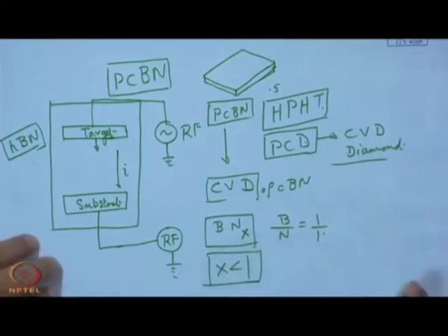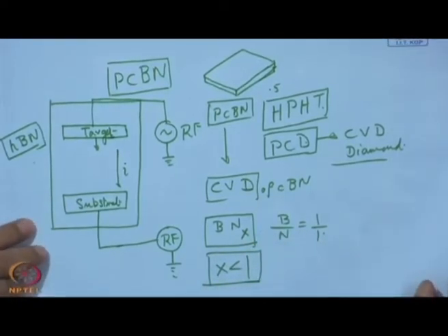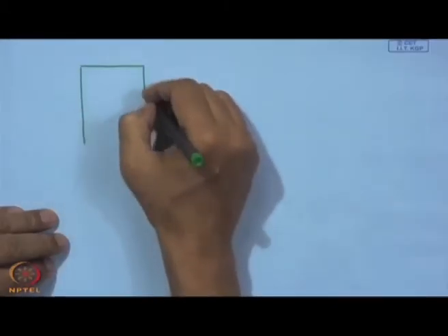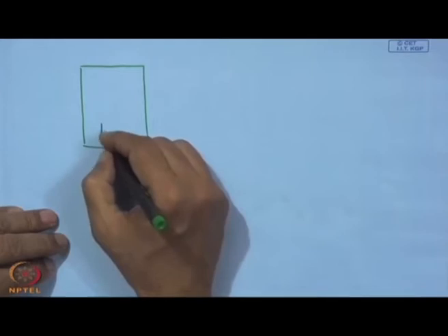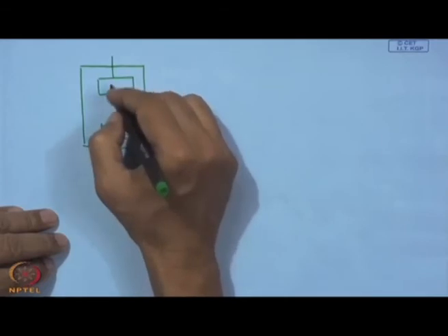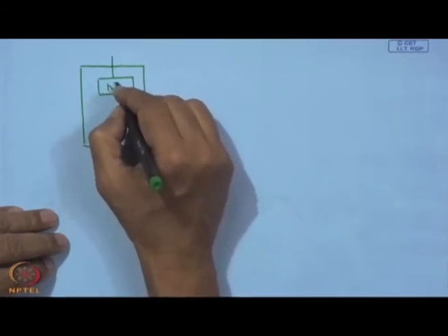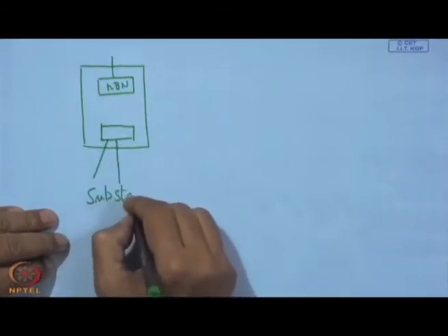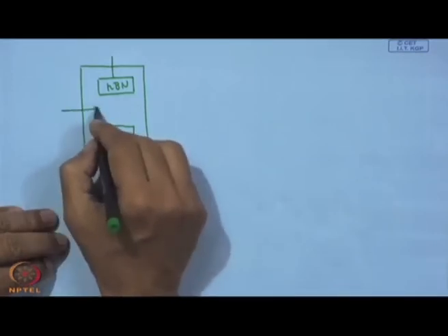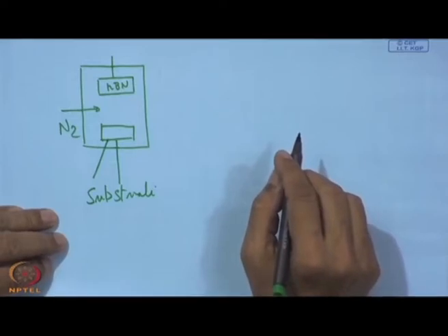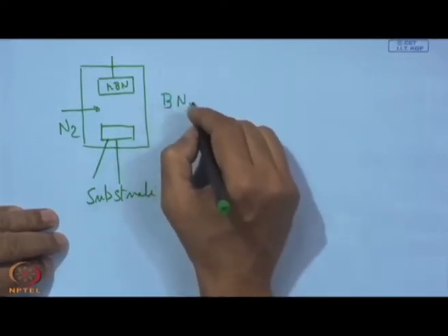So, what is to be done for rectification of this? You have partial admittance of nitrogen with this process, and this entry of nitrogen may make up this deficiency what we find as BNx.